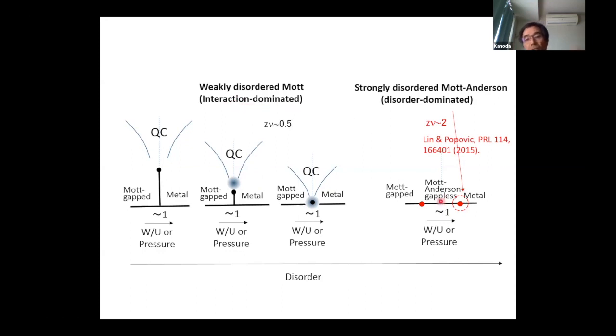But if we increase the disorder more and more, maybe this is separated into two: a metal-insulator transition and a magnetic transition. And in these regions, maybe Popovic deduced a Z nu of 2, which is the exponent of the disorder-dominated case. So we think that we may see some change from this value to this value if we increase the disorder.